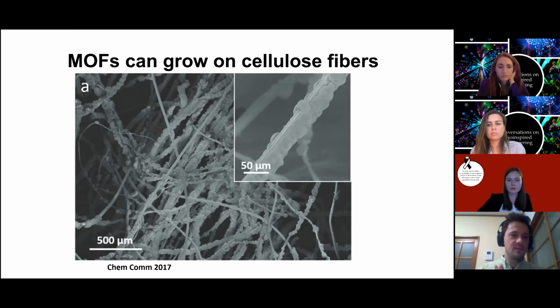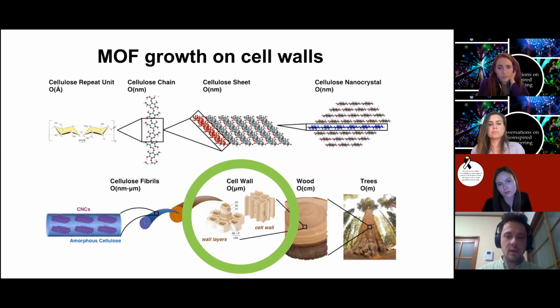So the fibril is sort of like a Janus particle or binary, where you have this fibril and then you have the particles all on one side of that. Some fibrils, if you look in, are completely coated, some aren't. And a lot of this has to do with wetting phenomena and adding a little bit of solvent to make sure those precursors mix better. But it shows us that there's a lot of promise for scaling this up to more complex, larger systems.